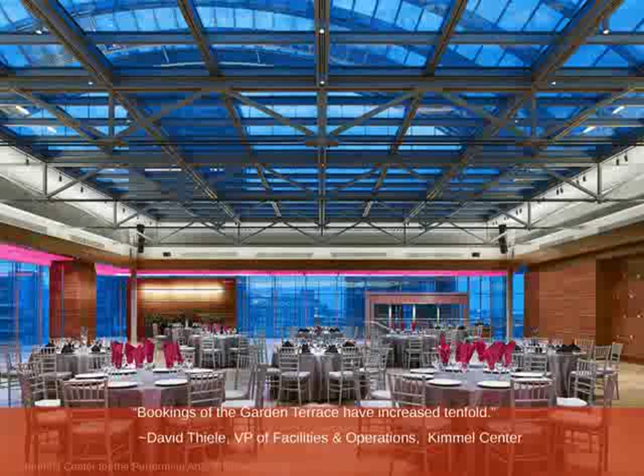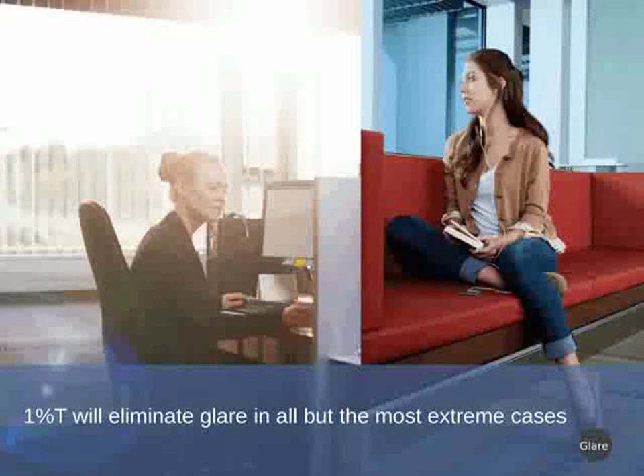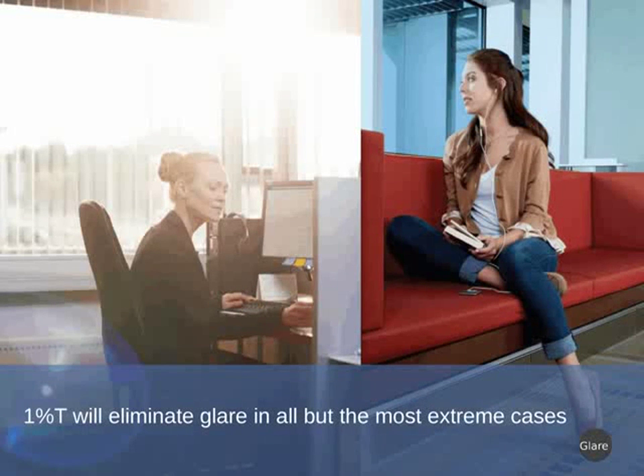So again, I mentioned that 1% is important just to keep in mind. We have studies which show that anything greater than 1% will still create a glare problem. So when this technology was first being pioneered, we were experimenting with levels of 10 to 3 and 2%, but we found out that even at 2%, it was still a problem. But at 1%, the orb of the sun, obviously we wouldn't recommend looking at the orb of the sun, but it would not create a distraction for someone focusing on a primary task. So that's, again, why 1% is important when you consider a solar control or a glare or heat solution.